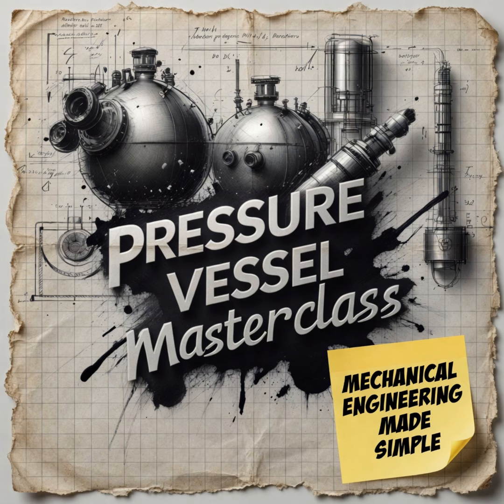That's a catastrophic blind spot. You could have an engineer standing 3 feet away with a clipboard, verifying the pressure gauges, thinking everything is perfectly fine because the water is only 40 degrees, and the vessel just detonates. It highlights exactly why the material category of failure analysis is so critical. The designer blindly selected a standard low-carbon steel without adequately analyzing the thermodynamics of the intended hydrotest conditions. The material was structurally sound for a warm operating environment, but it was a ticking bomb at 40 degrees.